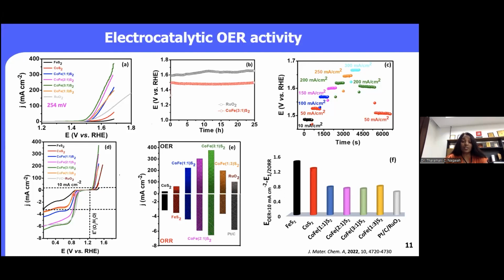It is very important to understand what is the potential difference, which is very important for the zinc air batteries. So therefore, what we have done is that you can see in this graph, we are calculating the half-wave potential with respect to the oxygen reduction reaction and the potential at 10 milliamp per centimeter square with respect to the oxygen evolution reaction. This bar diagram represents that both the OER and also the ORR activity is quite strong for the 3:1 compared to the other variants and also with respect to the ruthenium oxide as well as the platinum carbon for both these reactions.